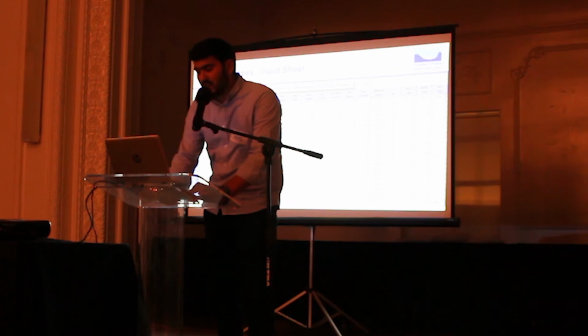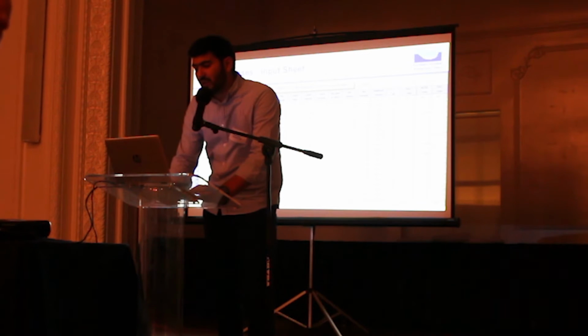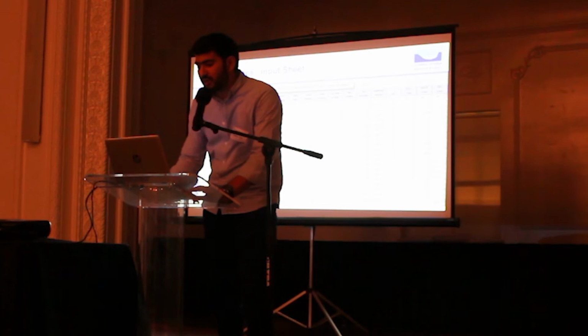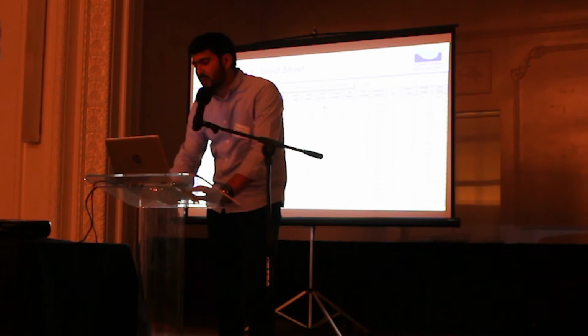Okay, so as you can see here, the first column from the left in the program has a description where we can write a description about the case that we are running. Here we have the temperature, and there is a drop down button, as you can see here, where we can switch from SI units to English units and vice versa. Then we have CO2 partial pressure, the pipe diameter, pipe roughness, liquid rate, liquid density, liquid viscosity, gas rate, gas density, gas viscosity, interfacial tension, and here we have the column for pH.